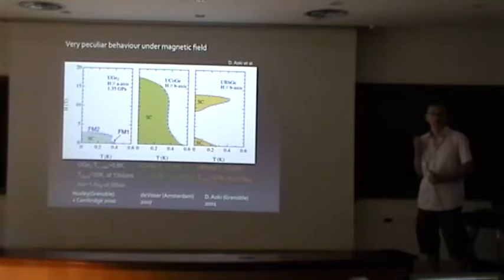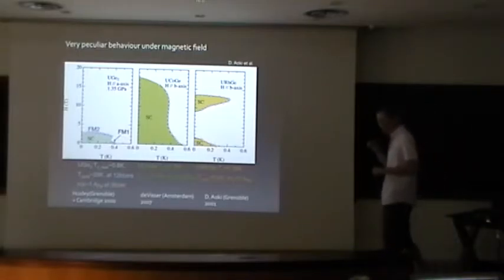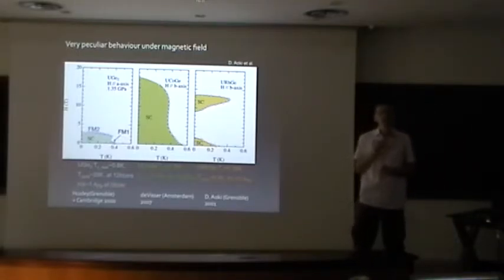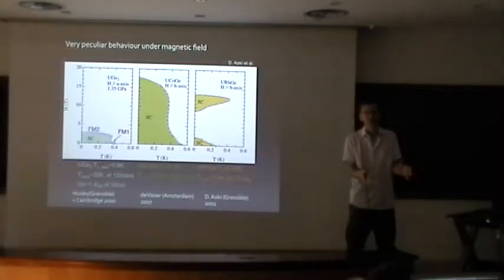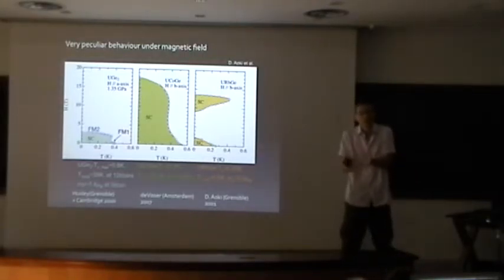Well, a couple of comments. The first one is kind of obvious, that in general, no one tells you which is the dominant band in the problem. As far as pairing is concerned, that can be very subtle. In heavy fermions, you usually know because it's the one with the highest f-electron concentration. But in general, it's not true. It's always very difficult to say something on the pairing mechanism. Yeah. But looking at this effect of multigap effects, you can also point out that some Fermi surfaces are more important than the others.